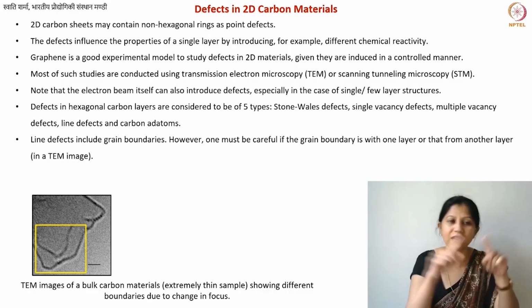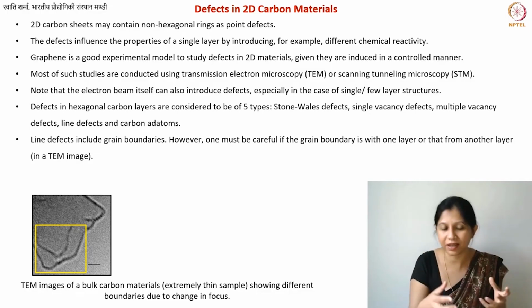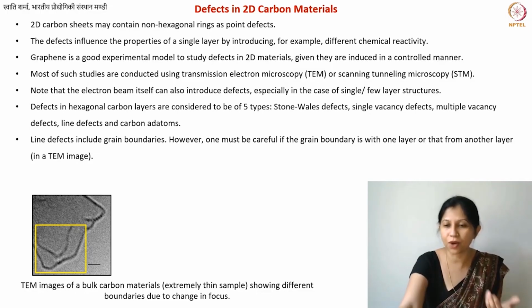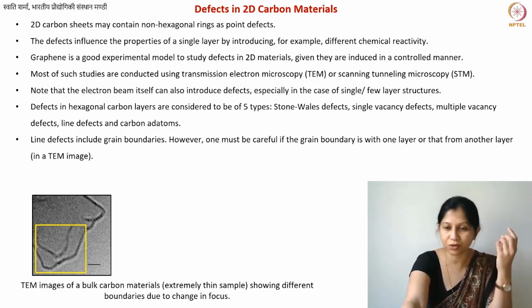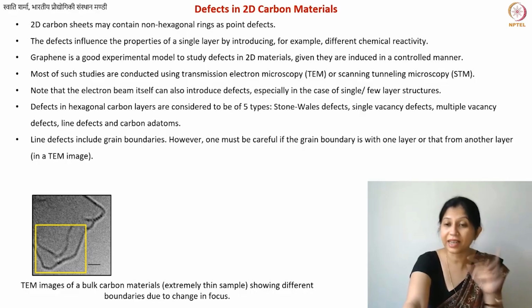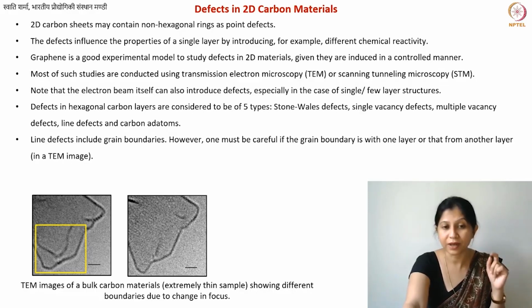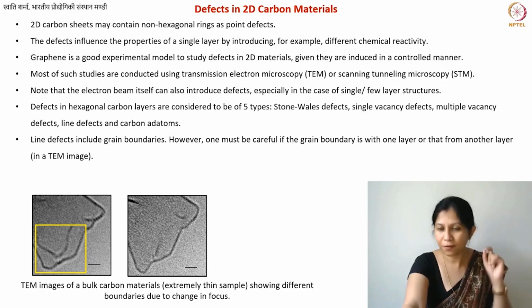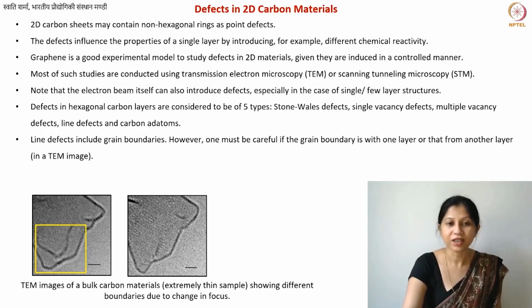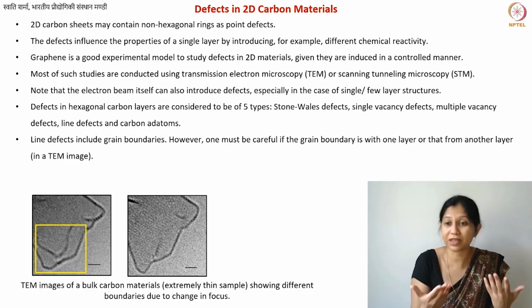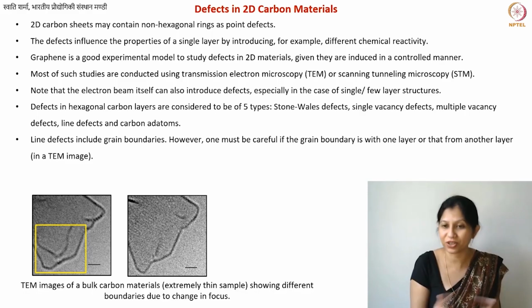Or at least the edges are brighter than the rest of the structure, because carbon material, and especially graphene, is transparent to optical light, and also transparent to electrons. So if it is a single layer, it's really difficult to image it. See the second image of the same location just by changing the focus. Same location. So in this particular case, you see that there's pretty much nothing visible, right? It's the exact same location.